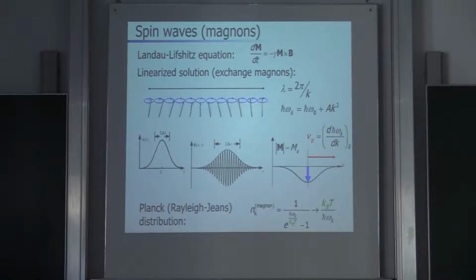Now, such a wave packet corresponds to a dip in the magnetization. The magnon is an excitation of the magnetic order parameter, which reduces the magnetization in the z direction. So this wave packet is a dip in the magnetization, and it moves with the group velocity, which is the derivative of this dispersion relation. Now, such a moving wave packet carries angular momentum, magnetization, it's a reduced magnetization, and also energy associated with that.